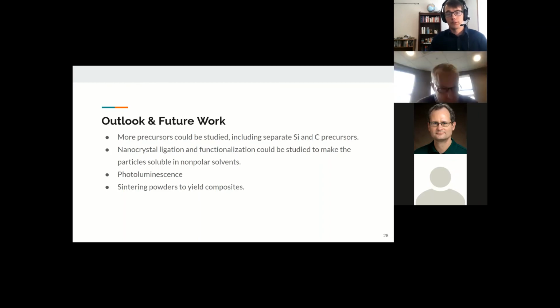In summary, silicon carbide is an inert substance which requires high synthesis temperatures. We made small silicon carbide nanocrystals without heating bulk amounts of material by utilizing energetic surface reactions in a non-thermal plasma. We collected crystals with sizes between 1.5 and 4.5 nanometers with both silicon-rich and carbon-rich shells. The amorphous carbon shells were removed by thermal oxidation, which increased particle solubility in alcohols.